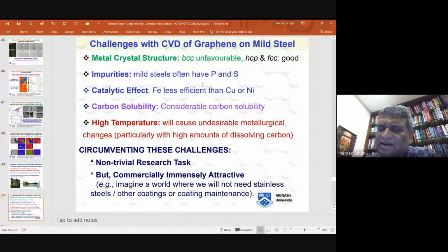I don't know whether there is any metallurgist in the audience, because at 1000 degrees Celsius, mild steel will have face-centered cubic structure, but at room temperature, it has body-centered cubic structure. That's fine. That's a metallurgical fact. But the problem happens because face-centered cubic structure at 1000 degrees Celsius has 100 times greater solubility of carbon compared to body-centered cubic structure at room temperature.